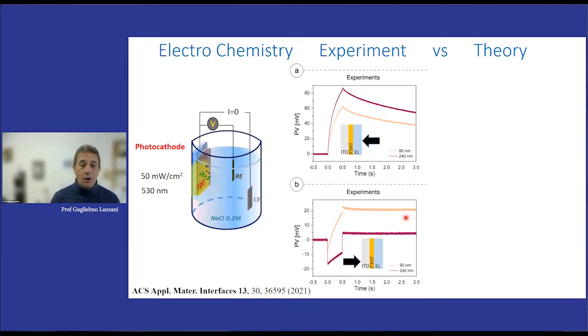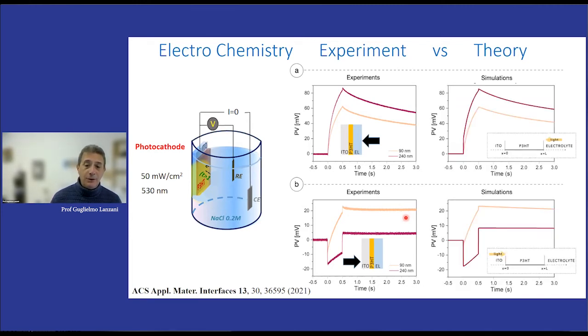It turns positive only if the sample is thin enough. If it is too thick, it doesn't have time during the illumination to turn sign. So we developed a model, and you see here on the right, before I tell you the detail of the model, that we can reproduce very well the experimental data, right? So we see the photovoltage and the time dynamics of the photovoltage when we illuminate from the electrolyte side and from the other side.